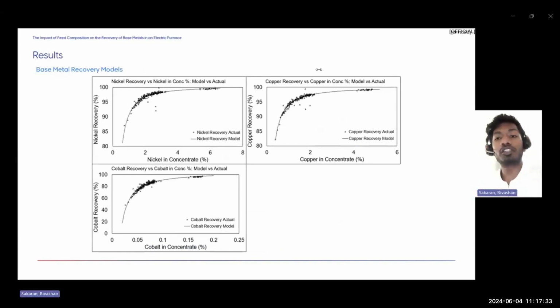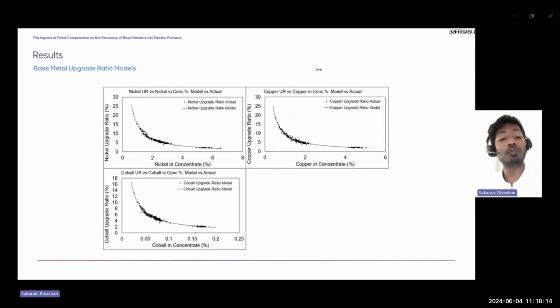In order to understand why we would see those differences at the lower iron concentrations, it was thought to use a data-driven model, that regression analysis, to get a better idea of predicting recovery, since the theoretical model, especially at lower base metal concentrations, did not match the data. So a data-driven model was used, and it can be seen that the data-driven model, especially for base metals, fits the data very well. And the same can be said for the upgrade ratios as well. This fits the data very well based on the data-driven model.